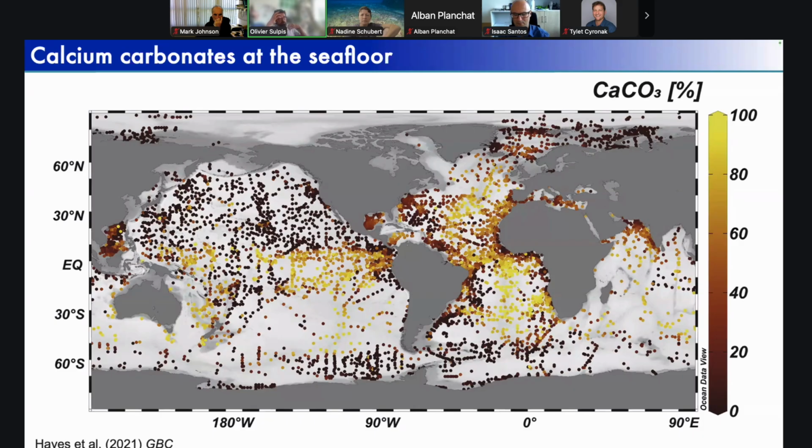We can see the influence of the environment here, mostly in the fact that the Atlantic, if we sum up, is mostly yellow. Calcium carbonates are well preserved in this basin. And on the other hand, the north of the Pacific is mostly black. Those minerals are mostly dissolved.